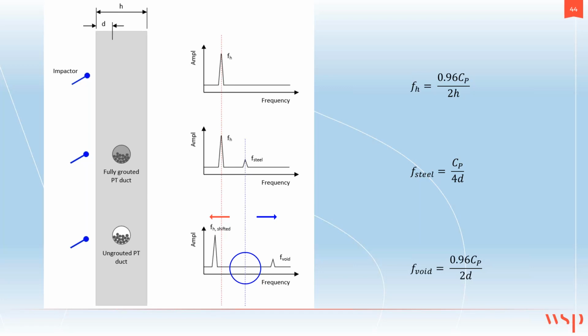It's important to note that looking at these two pictures, the void and the duct are obviously placed in the same location compared to the test surface, but they have completely different characteristics, which is why it's important to do these calculations before going to the field to know exactly what to expect and how to interpret the results. It also shows why it's important to do impact echo analysis in frequency domain as opposed to time domain.